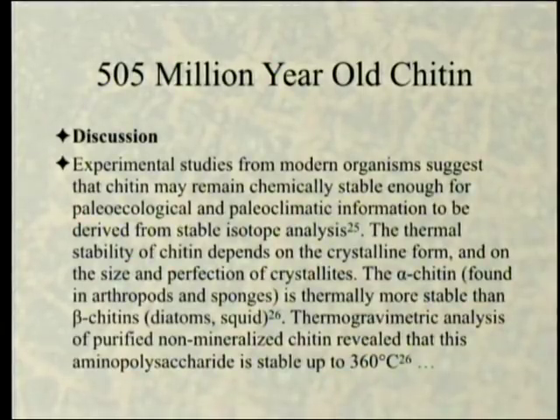Discussion. Experimental studies from modern organisms suggest that chitin may remain chemically stable enough for paleoecological and paleoclimatic information to be derived from stable isotope analysis. You can take this stuff and you can find out what the oxygen-18 isotopes were on it. The thermal stability of chitin depends on the crystalline form and on the size and perfection of crystallites. The alpha chitin found in arthropods and sponges is thermally more stable than beta chitins that are found in diatoms and squid.